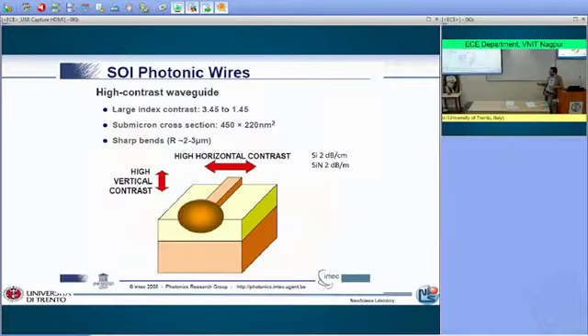With silicon nitride, those numbers are quite old, because nowadays they are able to make optical waveguides with losses that are measured in dB per meter. Yes, this is the number: dB per meter, okay? Silicon, dB per centimeter; silicon nitride, dB per meter, okay? So it's a huge difference. It's a factor of 100. And this is the reason why in quantum photonics, where each single photon counts, people are trying to use silicon nitride. Because you lose a very small number of photons by using silicon nitride, okay?